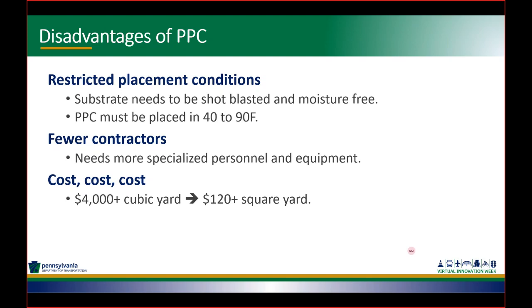And I think that the biggest disadvantage is the cost. I calculated the cost for an average, medium-size project, and we're talking about $4,000 per cubic yard of PPC. That's equivalent to $120 and more per square yard at 1 inch. So $120 versus an epoxy overlay at around $40. We're talking about three times the cost. But again, this treatment is thicker and lasts longer, and you can correct even a little bit of the smoothness, or if you have some little bit of ruts in the deck.